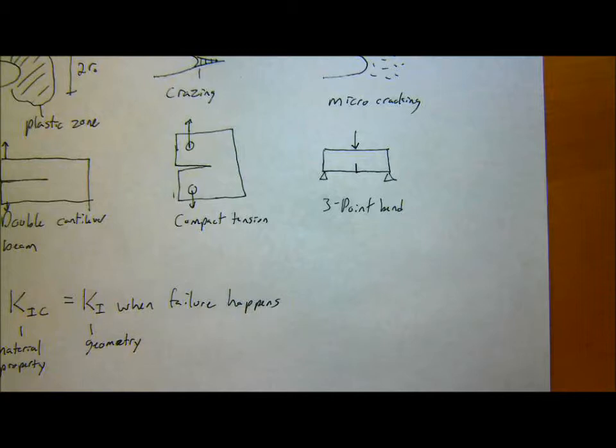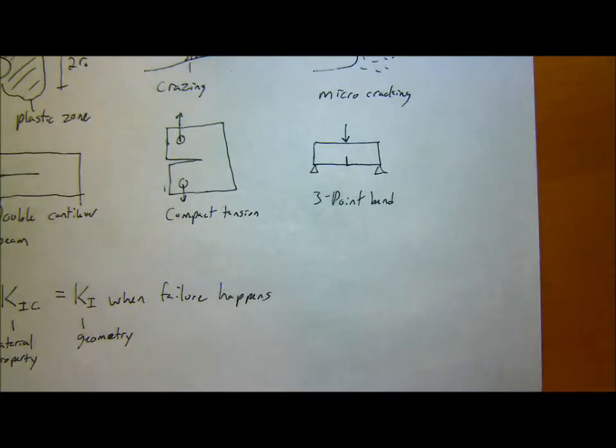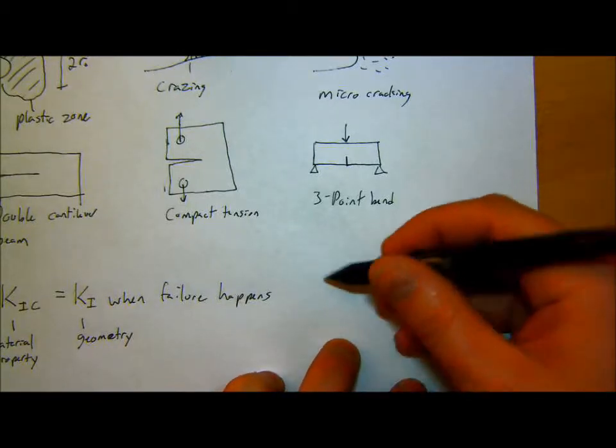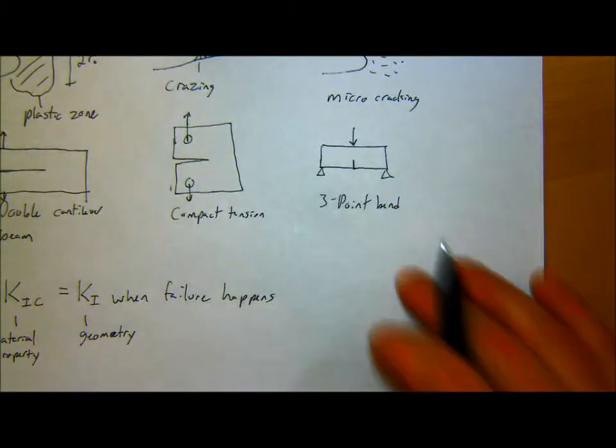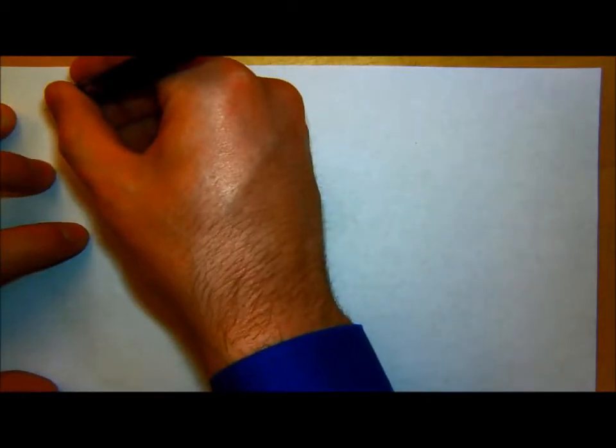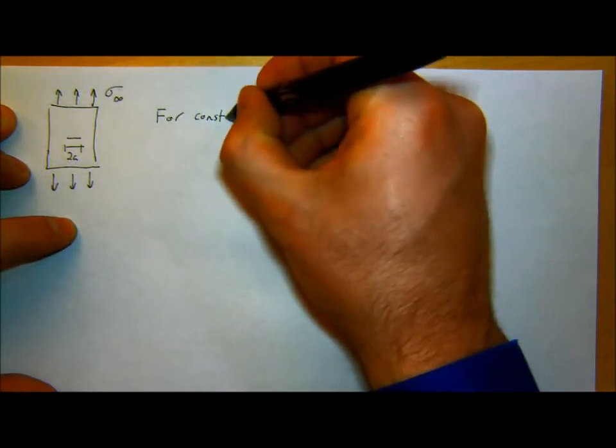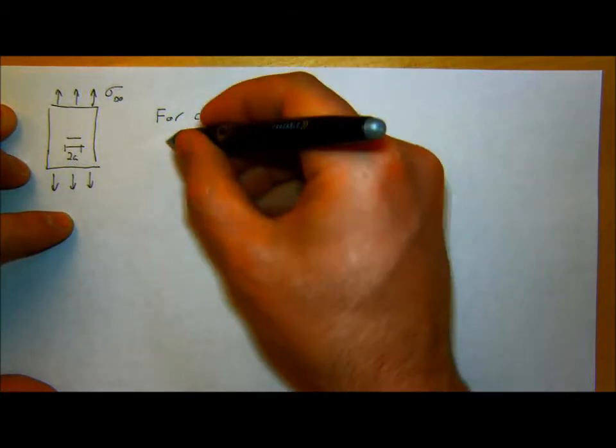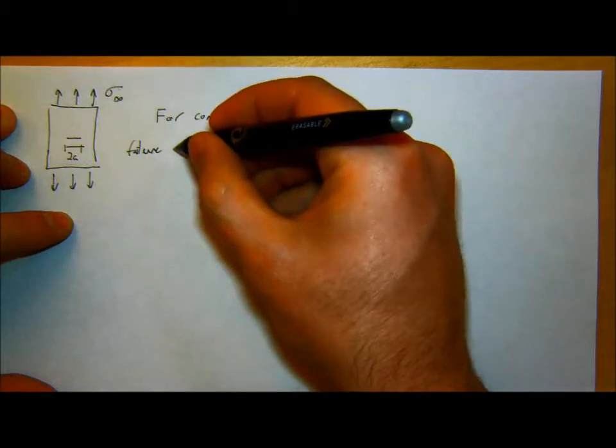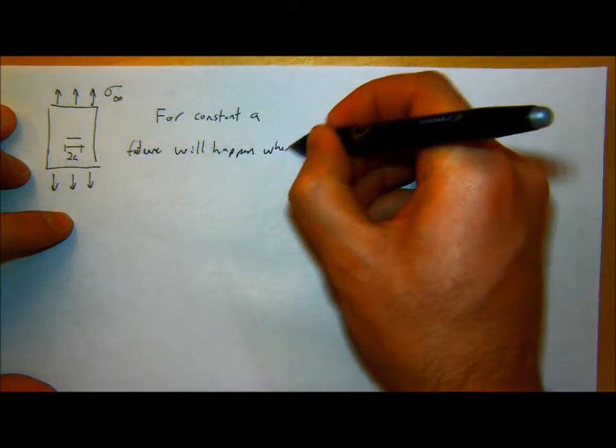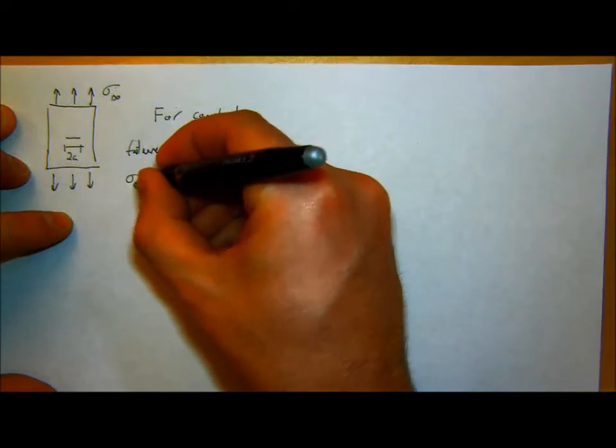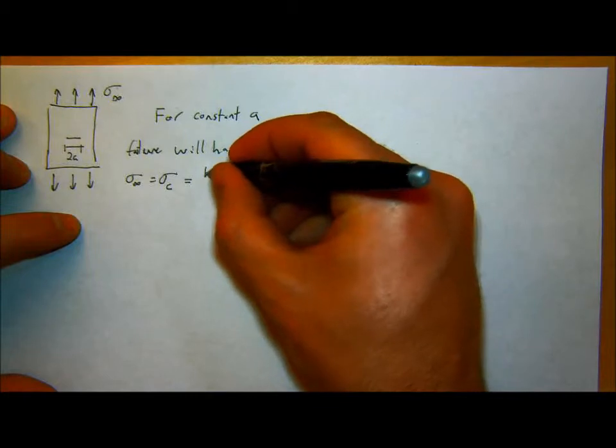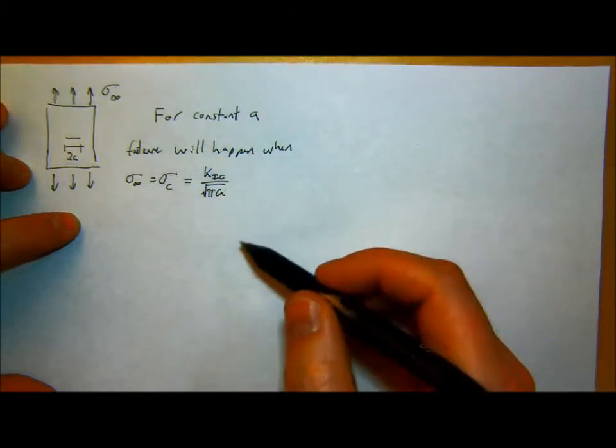but let's grab a new piece of paper. So if I have a plate with a crack internally of length 2a, and I'm applying some far field stress, some sigma infinity, for constant crack length a, failure will happen when stress infinity is equal to that critical stress, which is K1C over square root of pi a. So if I know the size of the biggest flaw in my material, I know how much stress I'll have to apply to cause fracture to happen. And that is then a material property.